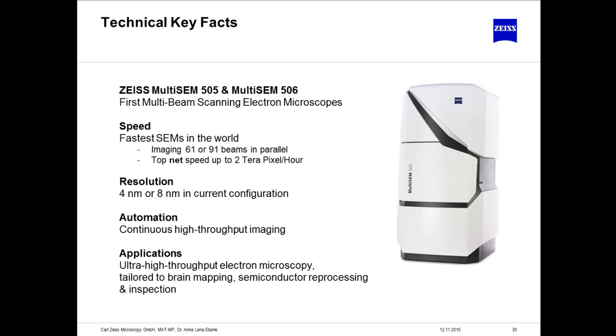The resolution is 4 nanometers with the 61-beam tool and 8 nanometers with the 91-beam tool. And this is something that is, of course, as compared to single beam tools, not that cutting edge, but it's a very dedicated tool for a certain set of applications, and that's what we started with. The degree of automation is extremely high, so we really aim for continuous high throughput imaging, which is not really 24/7, but we aim for 23/7, which would mean that after 23 hours of imaging, the machine would need an hour to go through its alignment procedures to set everything up again, and then imaging can go on.